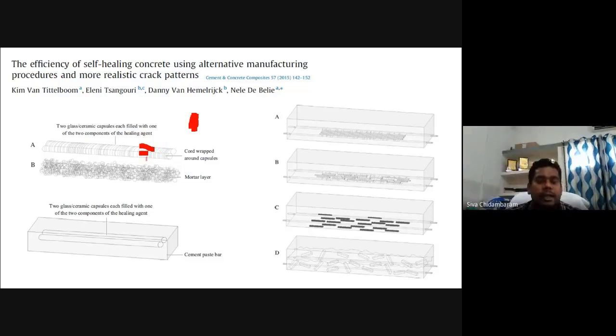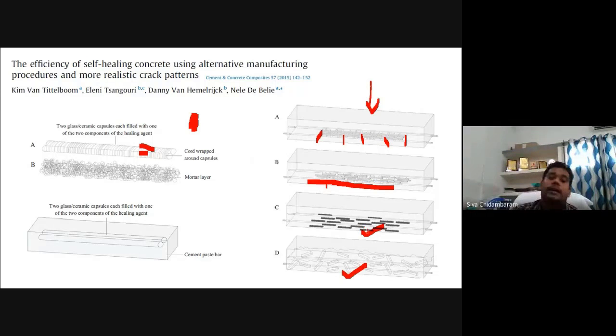It will be wrapped together, and then a small amount of cementitious layer will be applied, so that it will have wonderful bonding with concrete. Now you have a prism or you have a beam. Now what do we have to do? Generally, when you apply a force like this, you will experience a crack from the bottom side because there is a tension phase, right? So we are not going to have an immediate crack in the compression zone. Only in the tension zone we will have the cracks. So we have to place these capsules exactly at the bottommost points, like this. They have been kept perfectly oriented, and randomly distributed capsules.